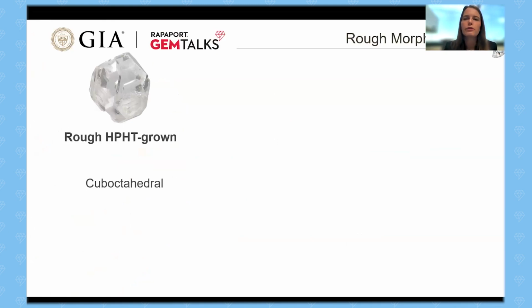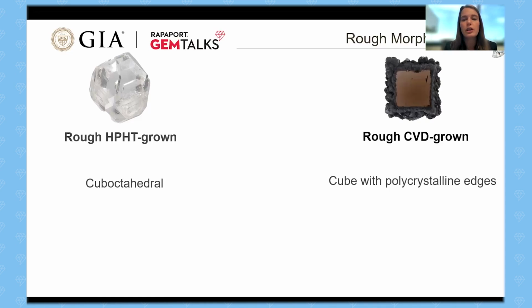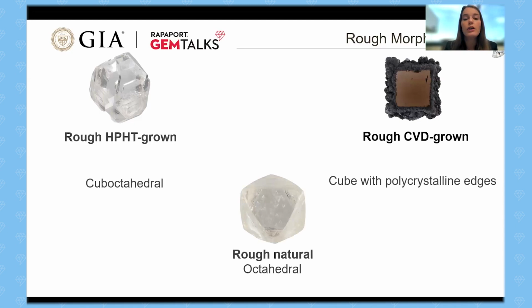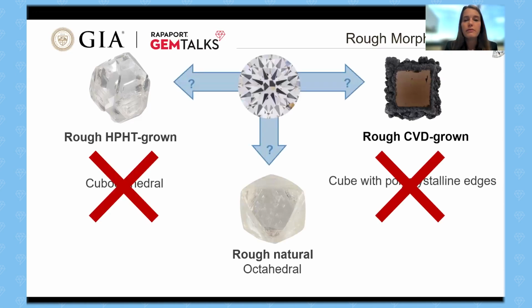Let's say you had a rough crystal in front of you. If it was a rough HPHT grown, it will have a cube octahedral growth morphology, so sort of a blocky nature to it. If you have your rough CVD grown diamond, you're going to have a cube, potentially with polycrystalline edges. It doesn't look particularly appealing here, but it could be treated to decolorize it. And then you could have a rough natural diamond, which could potentially have a very characteristic octahedral growth pattern. So these could be visually identified, but if you cut the stone, you've lost all of that information. So what do we have?